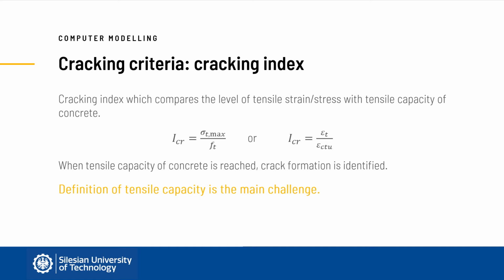One of the choices is to operate with mean tensile strength, while others advocate to use 5% quantile value to account for the effect of the weakest link. If formation of the crack is expected to happen in a certain location, localized strength reduction is introduced, which is an analogical concept to the introduction of the notch in the beam.